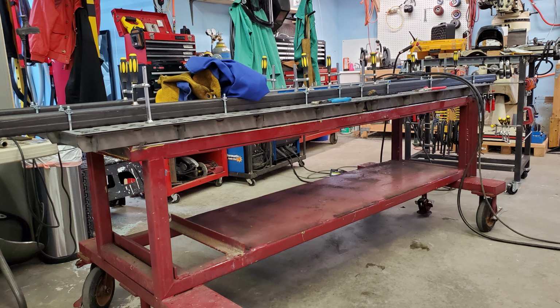The next step then is welding the tables to the red frame base. I tack welded the corners, but because of the sagging middle of the red base, the gap was too large to weld along the sides at the bottom of the upper table's ribs along the rest of the length. I was also concerned that by welding the bottom of the ribs horizontally to the red frame, the ribs would be pulled outward at the top and warp the tabletops too much.